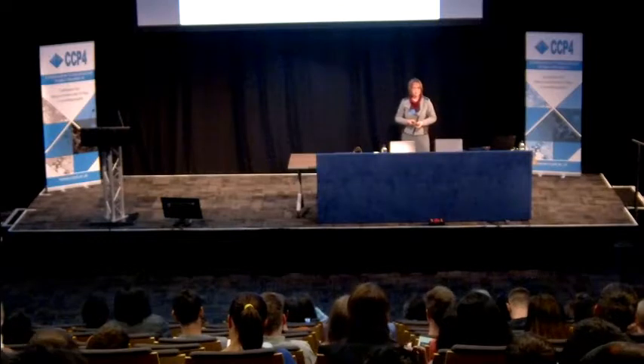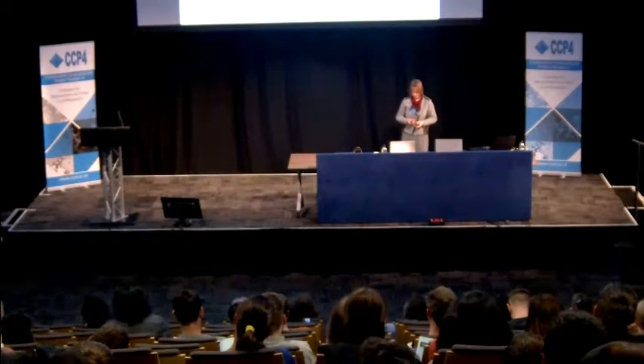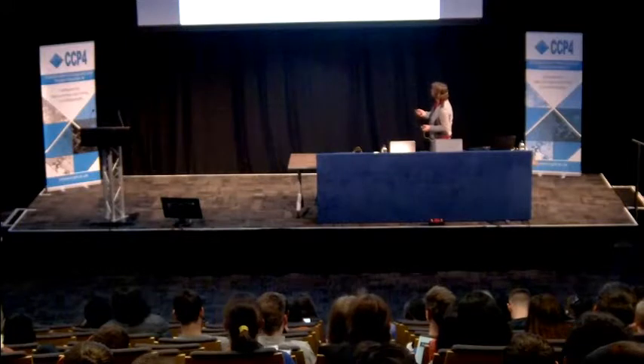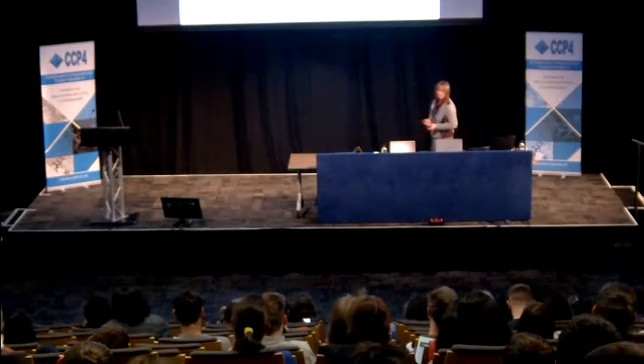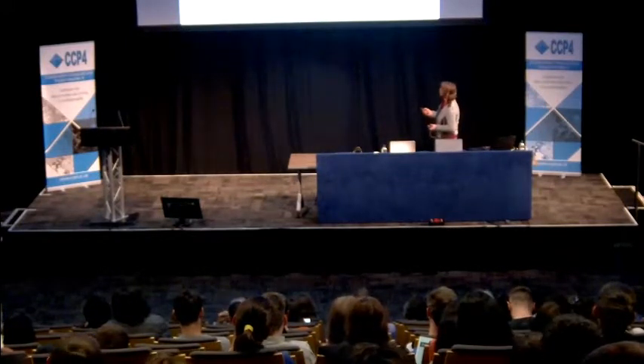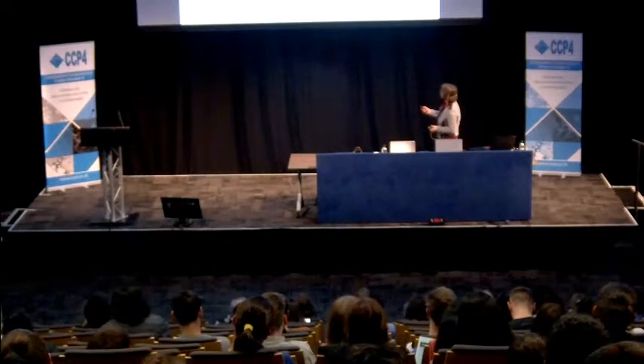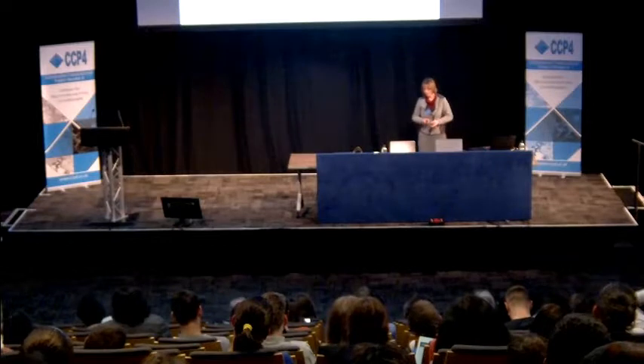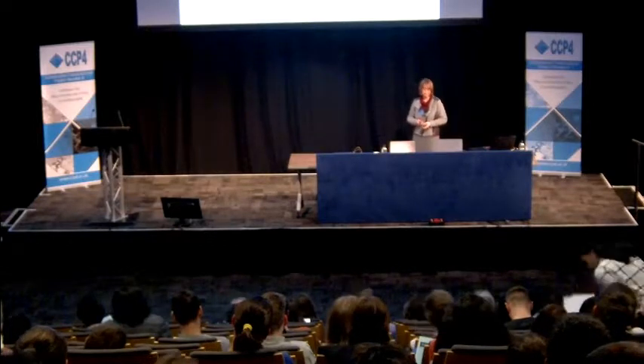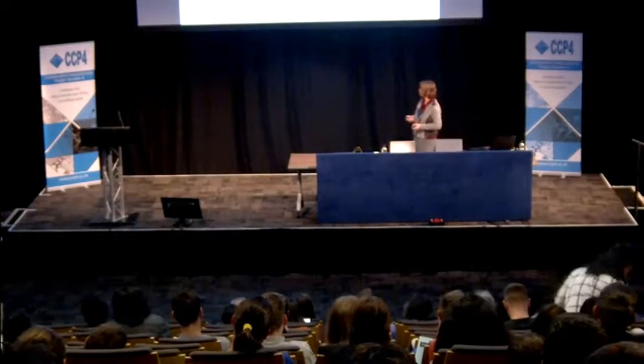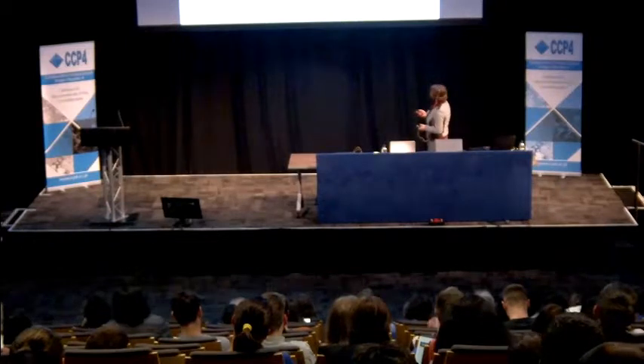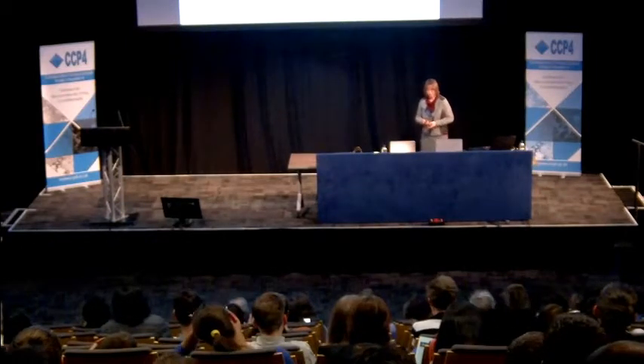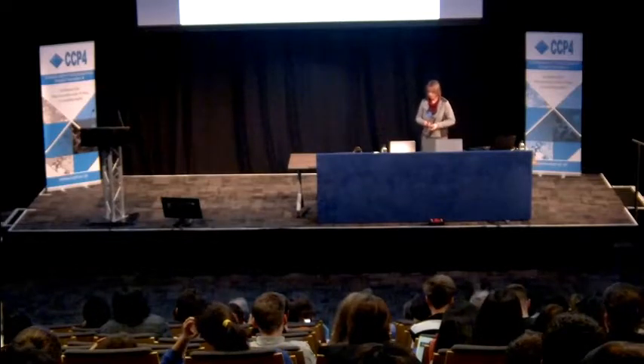Let me explain that with a simple two-dimensional example. We have here two orientations: a blue orientation and a red orientation. The symmetry operator which transforms blue into red is this two-fold axis, and in matrix notation this would be minus 1, 0, 0, 1. The fractional contribution of the blue domain is 5 over 9, while it's 4 over 9 for the red orientation.